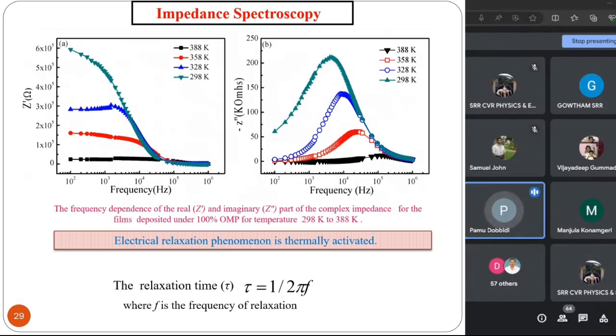Yeah, here also we want to look at it: compared to the bulk, here the resistance is lower. When we look at the impedance spectroscopy, why? Because in the case of bulk material, as I showed you in the previous section, the grain size is about 3.3 microns, but here the grain size is about 30 to 40 nanometers, and that's where you see that the grain boundary response is increasing here. That is one thing that we need to note in the present case.